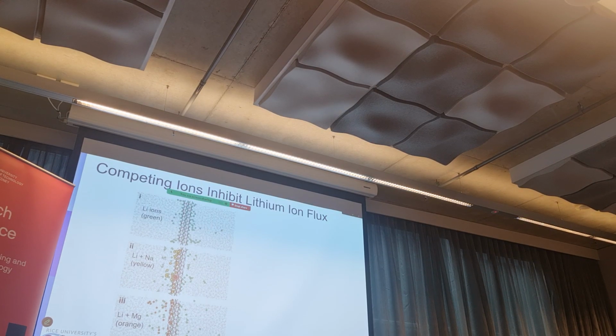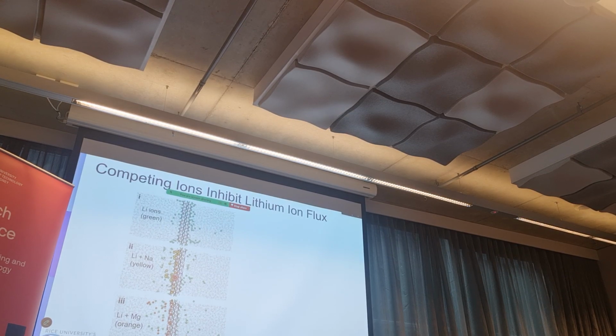What's happening is that when sodium gets there, it occupies some potential partitioning sites, so lithium cannot find many of these partitioning sites to get in, and this is why the flux decreases. The same phenomenon occurs with lithium plus magnesium.